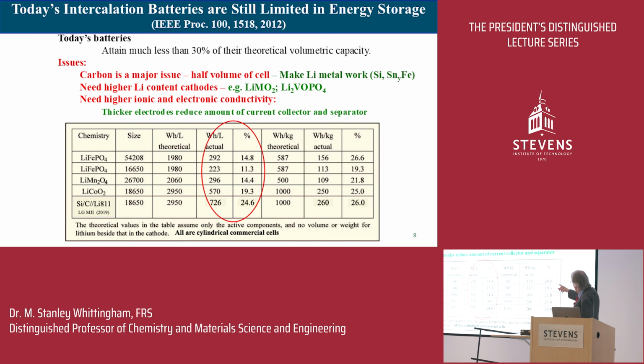So this lithium iron phosphate getting about 15%. The very best commercial ones are 25%. So 75% of the volume of your battery is dead weight, dead volume. Similarly, on the right-hand side, 75% is dead weight as well. Okay. So a huge incentive. Can we reduce this dead weight and make them much better?